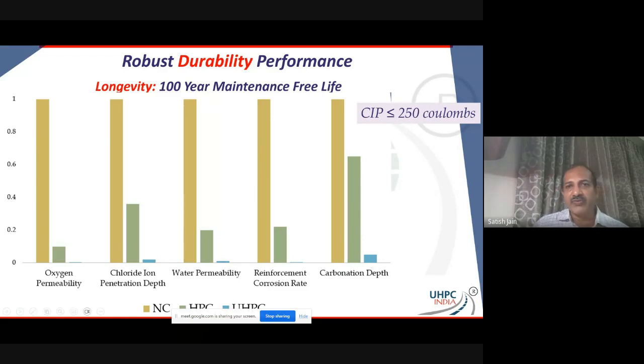So just to give you an example, if you were looking at a RCPT value, because a lot of you may be very well aware that when you do a rapid chloride penetration test and you allow the charge to go through, regular concrete could be anywhere like 3,000, 4,000 coulombs. It could be M25, M30 or something like that. As we go to a very, extremely high performance concrete, you're looking at numbers closer to 1,000 coulombs. But in general, UHPC will have less than 250 coulombs of charge passing through it. That's how tight it is. The particle packing of UHPC is extremely tight.